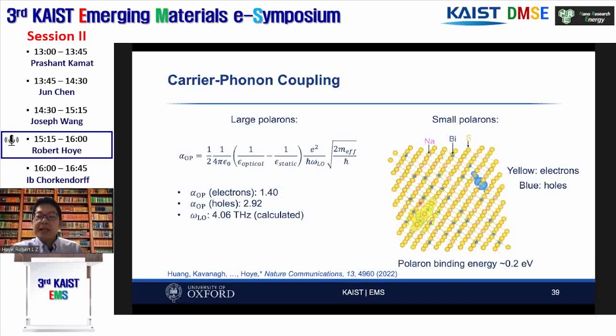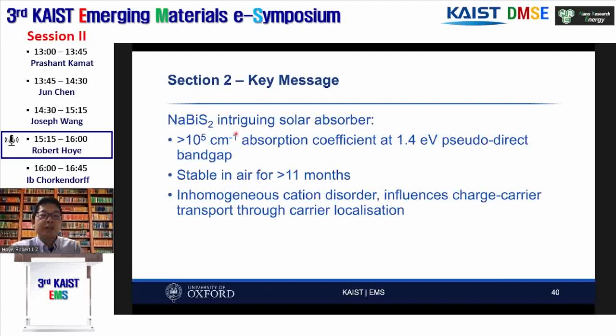On the other hand, the electrons cluster around the bismuth. So this explains why we don't see any PL from this material, because the holes and electrons hardly ever see each other. It also explains why, on the long time scale, we see such a very slow decay in the photo-generated carrier population, because it's very difficult for these electrons and holes to find a common defect state to recombine with each other. So the key messages here: sodium bismuth sulfide is a very intriguing solar absorber, has very strong